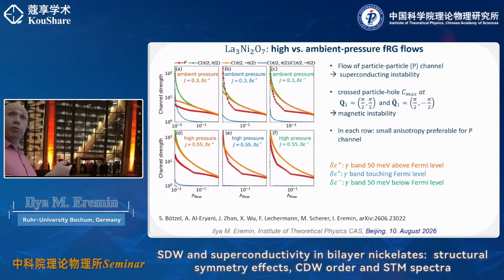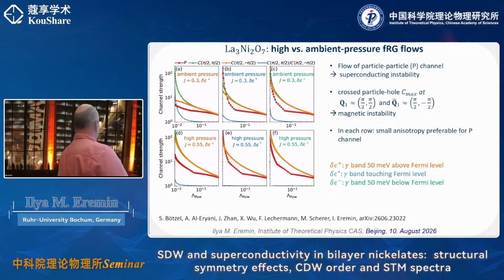And this is what you see very nicely with the FRG, which is picking this up. If you do it at the high pressure, you play around again with the position of the gamma pocket, but effectively, once you have this strong frustration, these two wave vectors frustrate, and it's easier for superconductivity to take over. Because frustration suppresses the long-range magnetic order.